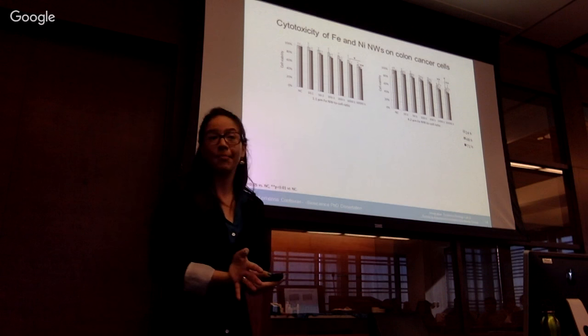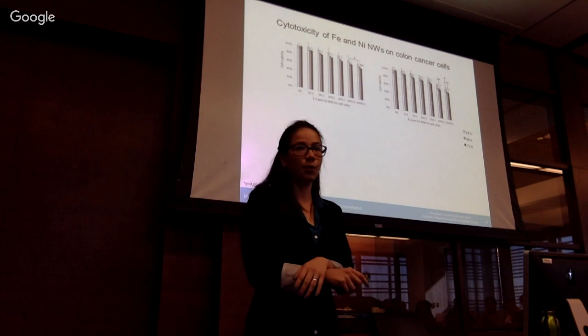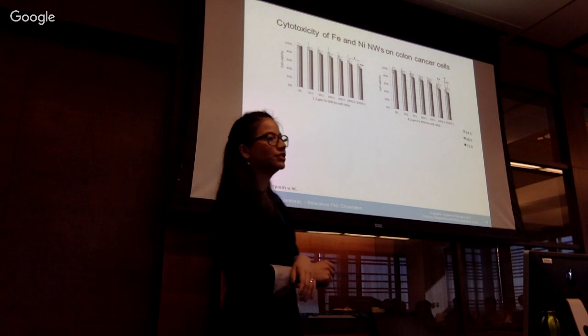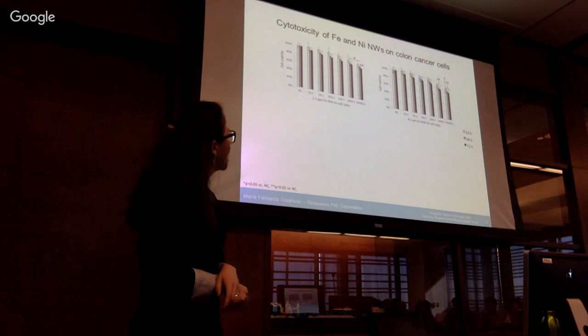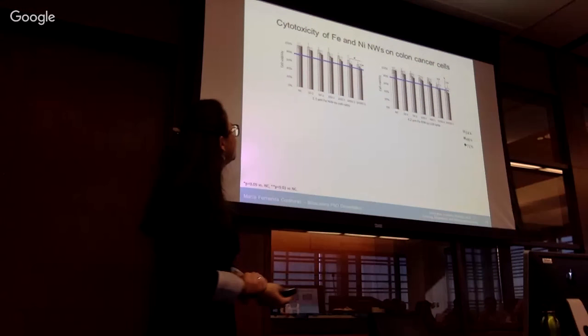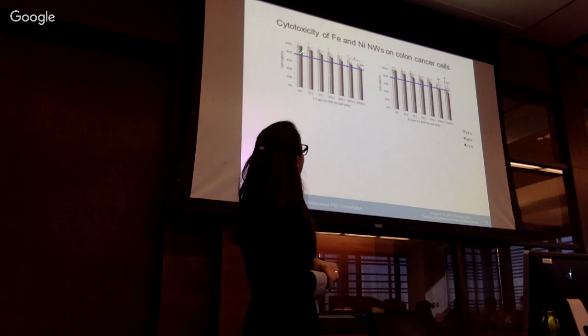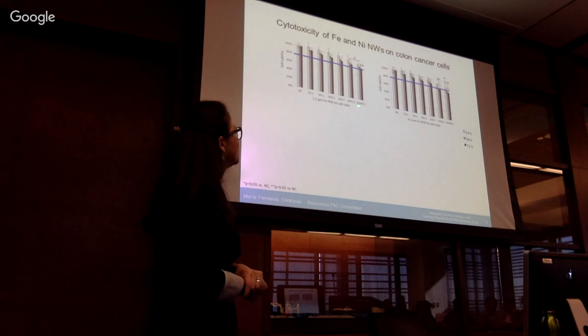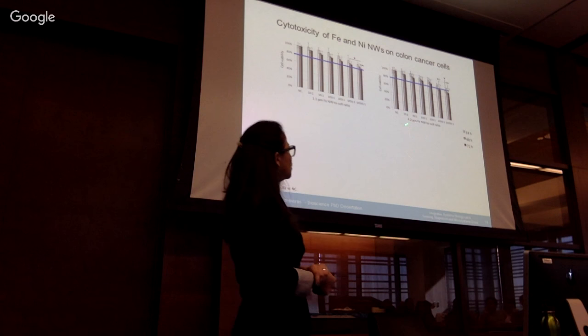We have our negative control in which we don't add any wires, so that corresponds to our 100% signal. And in the x-axis, we have different concentrations that range from 10 up to 10,000 wires per cell over here. And again, these are the results for iron. Taking a reference of the 80% mark, we can see that, for example, for the 1 micron iron wires, everything remains above the same. So no major toxicity is elicited, even for this very high concentration, at times up to 74 hours. And when we increase 4 times the length, we see that this is slightly different.